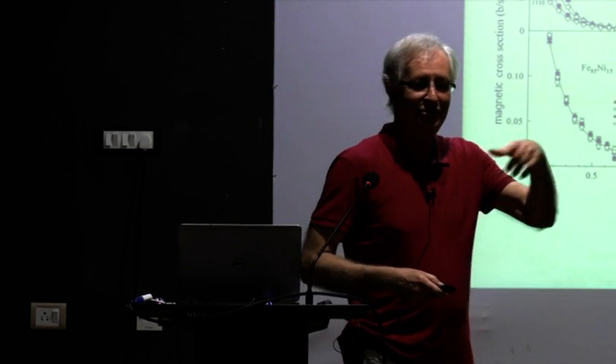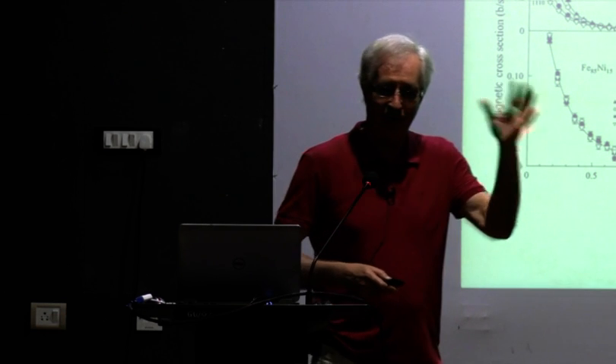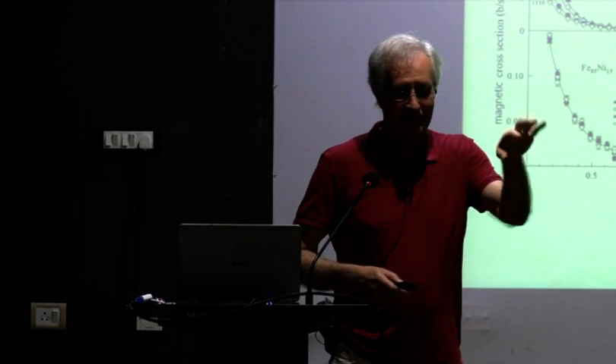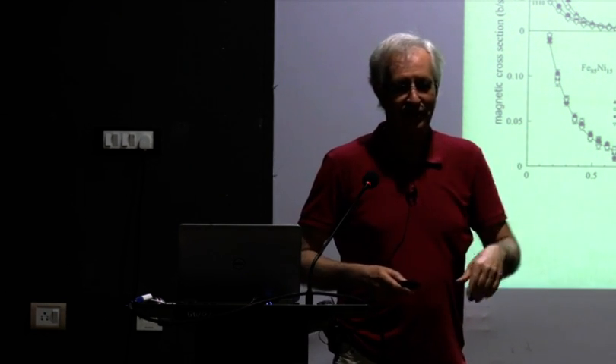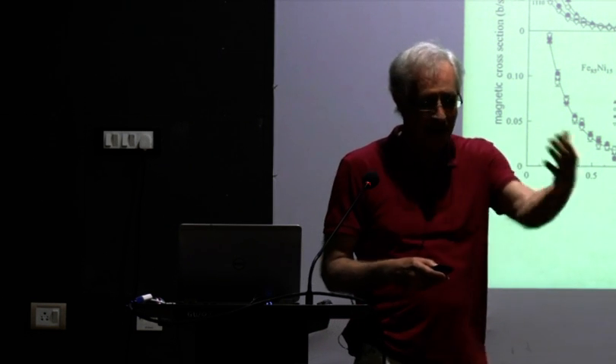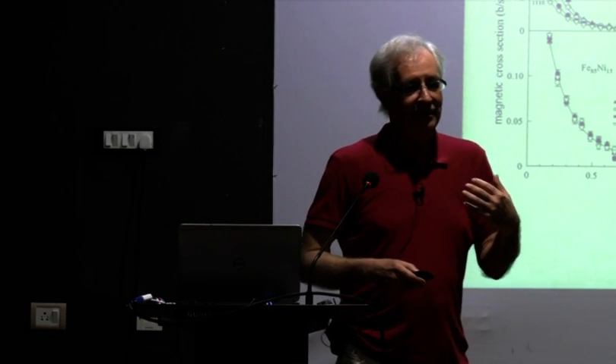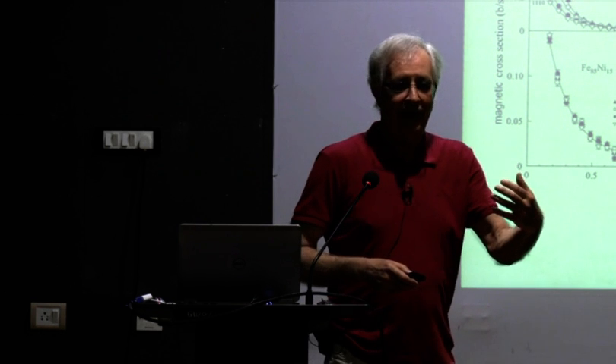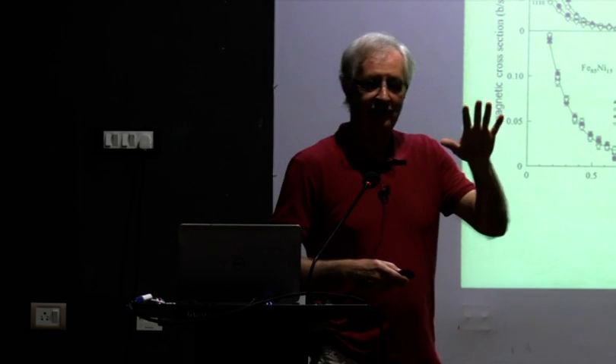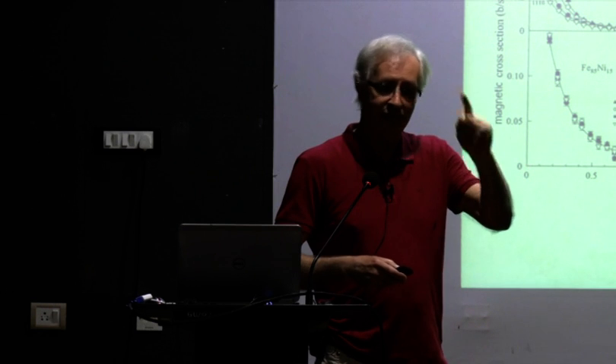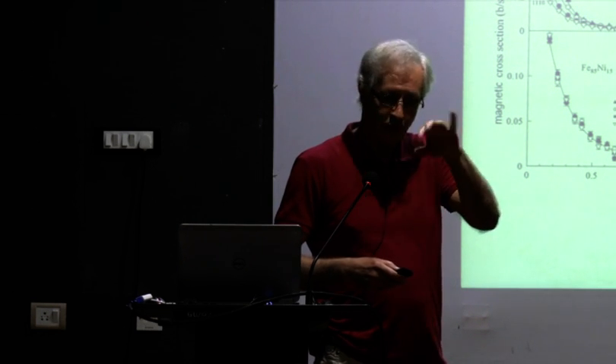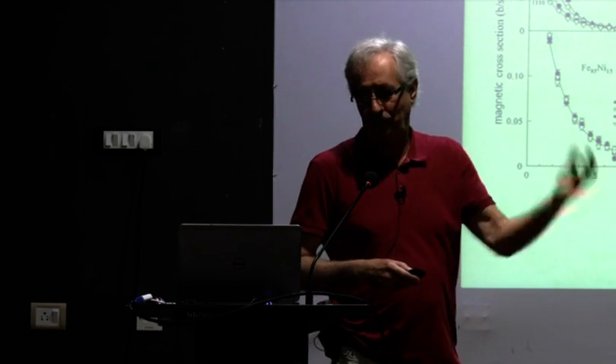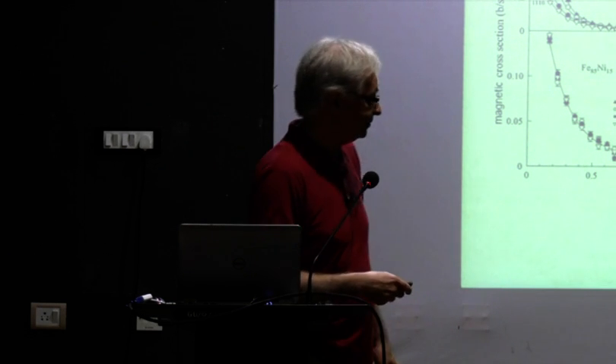So remember I showed you some polarization analysis experiments yesterday, how the spins come, they flip and you do all sorts of analysis, and then you can extract the magnetic part of the scattering, and depending on these features, then you can say you have long-range ordering, or you have short-range antiferromagnetic ordering, or short-range ferromagnetic ordering.